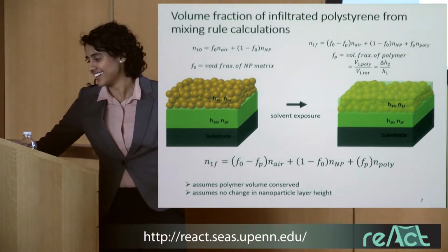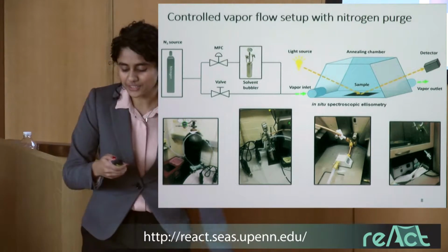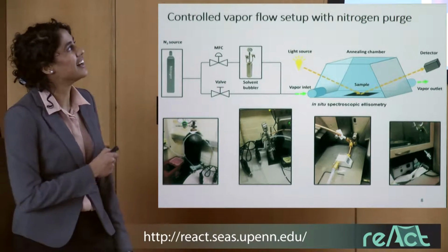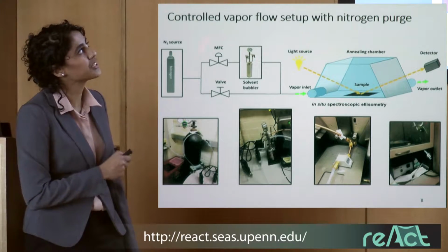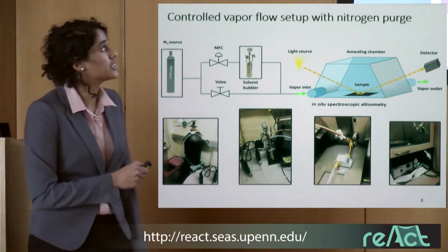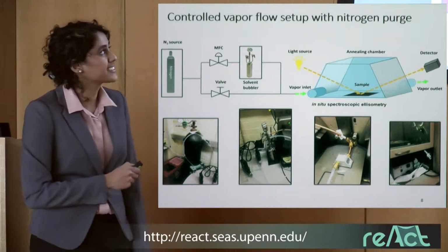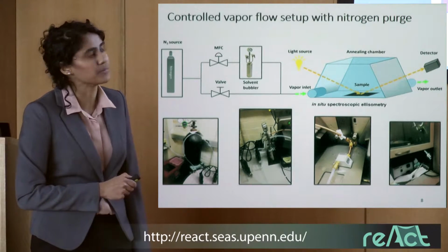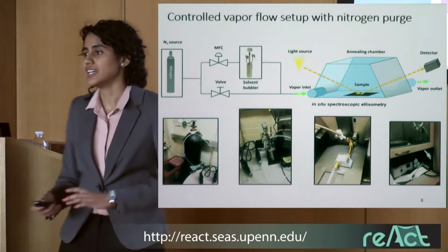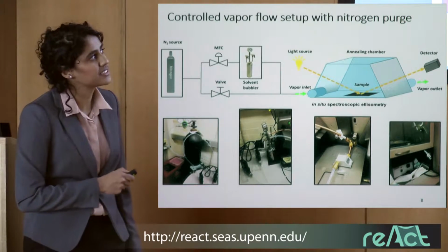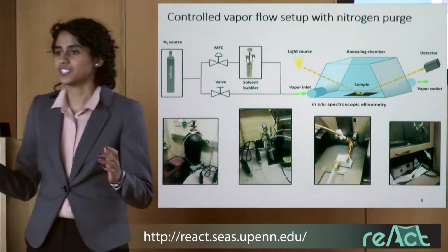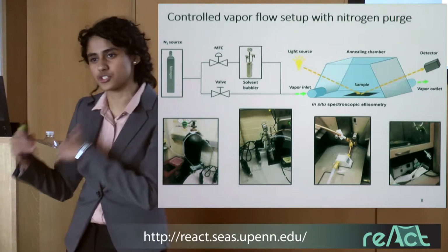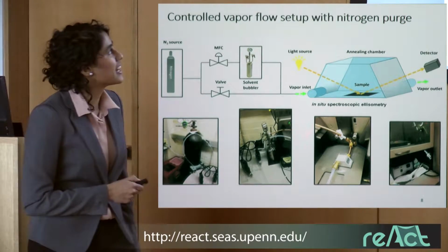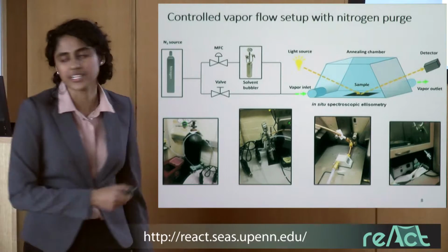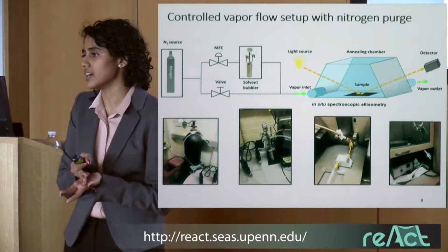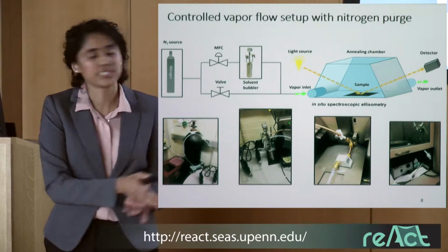All right, so the setup that I use is a controlled vapor flow setup where I have a nitrogen tank going into a mass flow controller that goes into my solvent bubbler and basically sends a controlled activity stream of my solvent into my chamber. And I can observe this via in situ spectroscopic ellipsometry, so I can actually see the dynamics of the infiltration as it's occurring. And then I also have this purge stream incorporated, so I can immediately quench my infiltration as it's occurring.